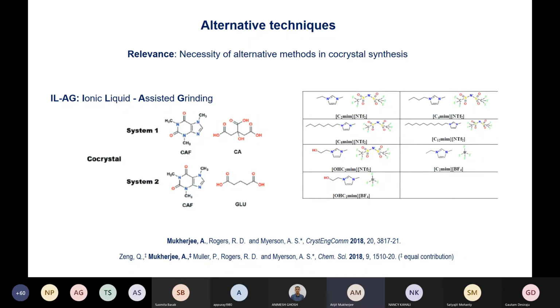So we mainly used C2MIM based ionic liquids in this study because they had shown very good crystallization propensity in earlier studies, which I have also cited here. We chose two systems basically. One is the caffeine and citric acid system, and the second was the caffeine and glutaric acid system. The citric acid system was chosen because it is formed only through liquid assisted grinding. And for the second one, the caffeine glutaric acid system, polymorphism occurs depending on the solvent system.